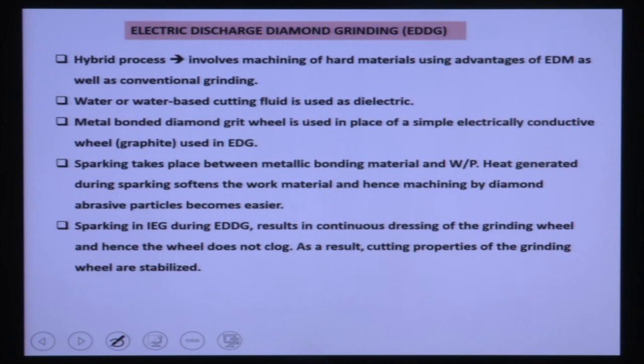So this hybrid process involves machining of hard materials using the advantages of EDM as well as conventional grinding operation. Water or water based cutting fluid is used as the dielectric. A metal bonded diamond grit wheel is used in place of a simple electrically conductive wheel like graphite, which is used in the EDG process, the electro-discharge grinding process. Sparking takes place between the metallic bonding material and the workpiece, and heat generated during the sparking softens the workpiece material, and hence machining by diamond abrasive particles becomes much easier. Sparking in the interelectrode gap during electro-discharge diamond grinding results in continuous dressing of the grinding wheel.